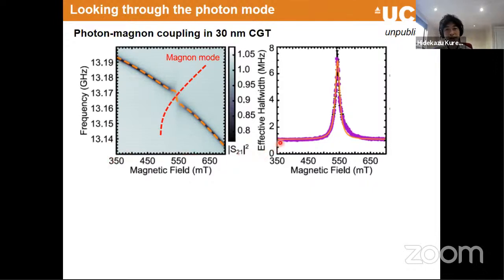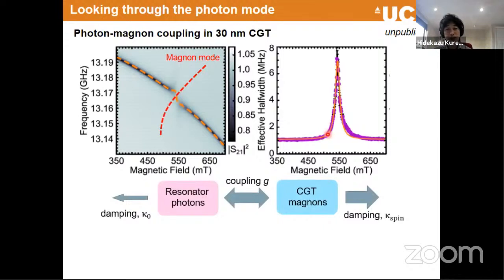When you analyze the line width as a function of magnetic field, you can see a beautiful Lorentzian peak. What I mean by that can be explained by this simple cartoon or block diagram. At this small magnetic field region, the resonator is resonating, but the magnet is not resonating at all. If you inject energy into the resonator to create photons, they simply dump into the reservoir by the resonator's own damping mechanism. But when you hit this resonance, the CGT magnon starts to resonate and couple by the dipole interaction. Then we start seeing the energy exchange between these two.